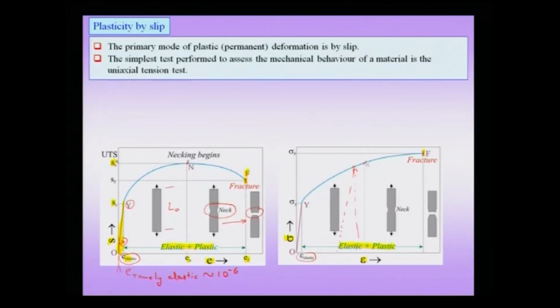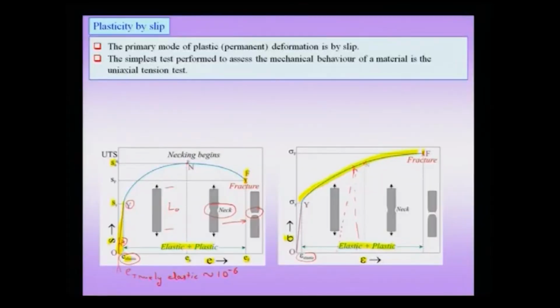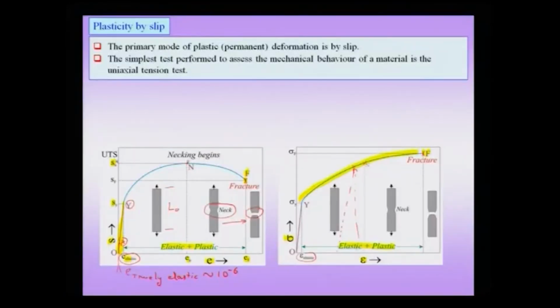There are a few things of course, we need to ask, which is why is this curve going up, the blue curve, and this phenomenon that the stress actually required for flow increases with strain is called work hardening or strain hardening, and that means the material is getting harder and harder as I am plastically deforming it, till of course, you reach a point like fracture. The reason, as we peek ahead, is because of motion of dislocations and the increase in dislocation density, and this intersection of dislocations making dislocation motion difficult.